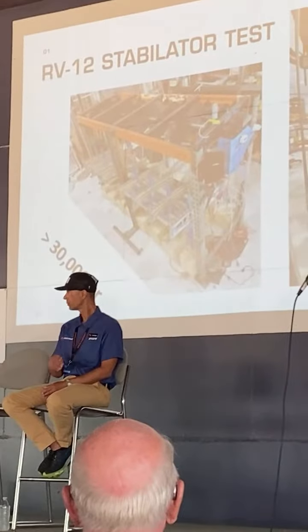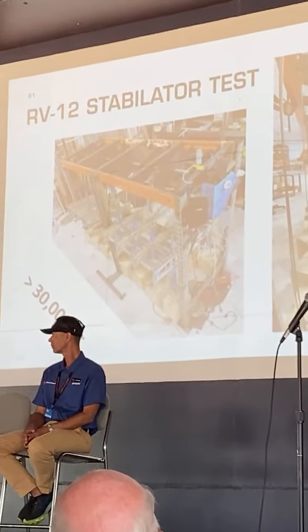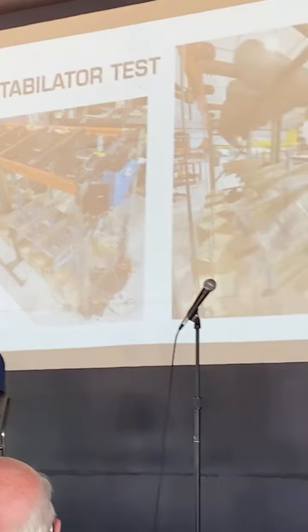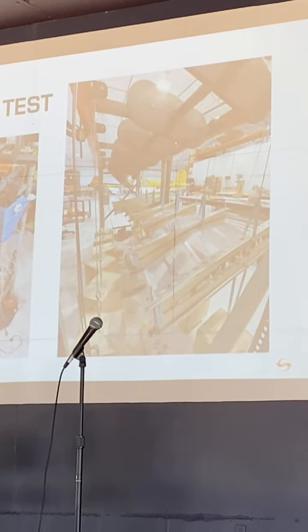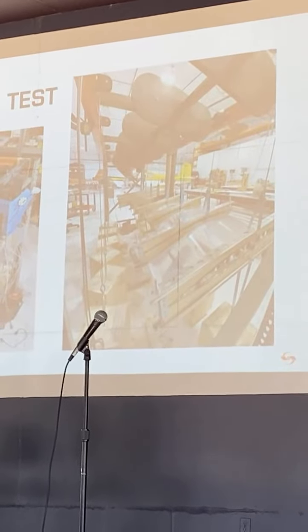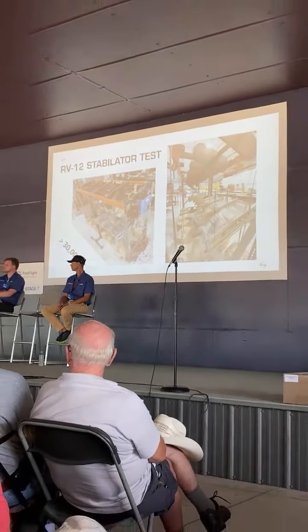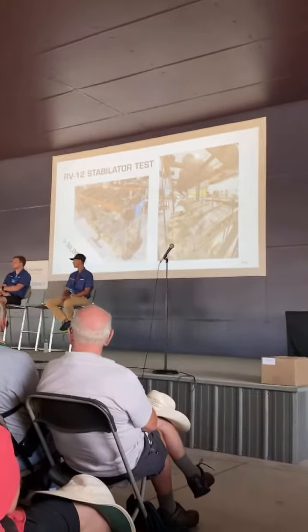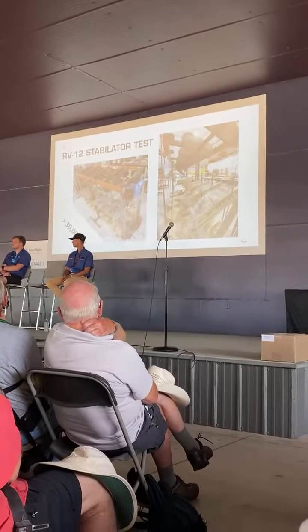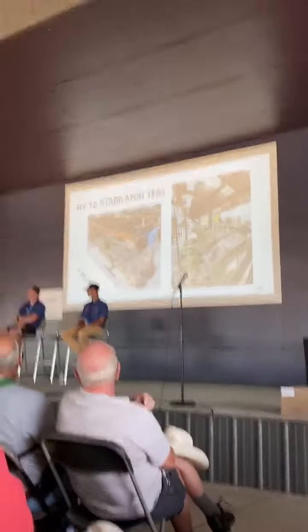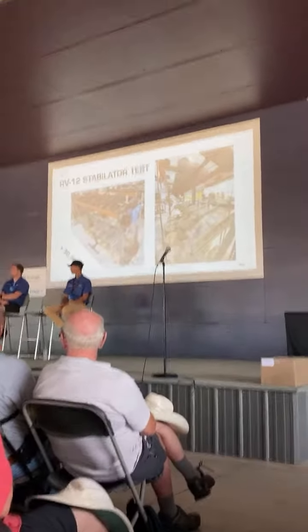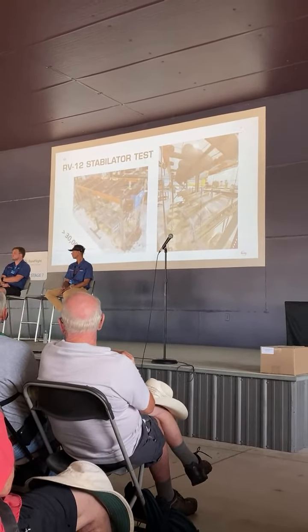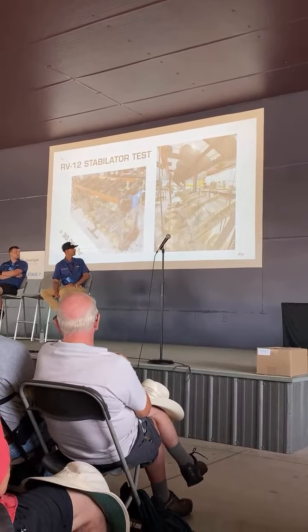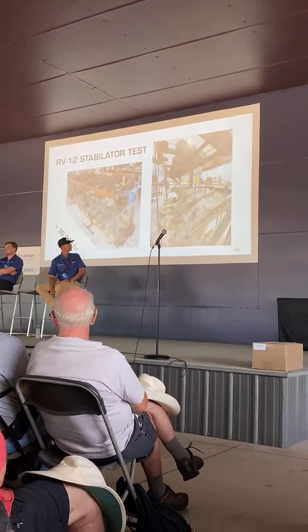This is the RV-12 stabilator test, and I'll get into this in a second here, but 1 hour in flight school is equivalent to taking the structure to 1 limit load. So all loads that occur during an hour equate, and there's an AC for this that I'll get into, to 1 limit load cycle. And we tested this to around 32,000 cycles when we finally turned off the machine. This had worst case rivets, laser cut holes in it. And why we tested the stabilator is in this structure, you have laser cut structure that's riveted to laser cut structures. So you have the worst case scenario.